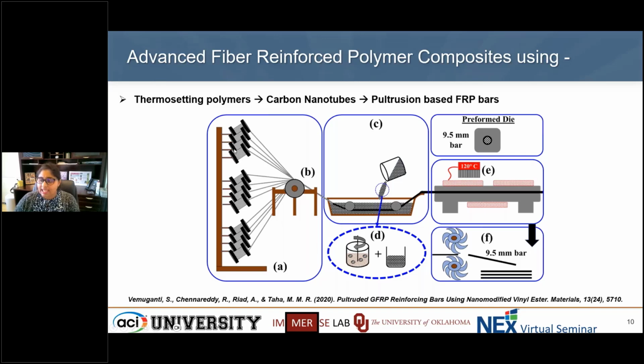We set up a lab-scale pultrusion method where we have an epoxy vinyl ester resin bath, which has fillers in it, which are carbon nanotubes. The way to achieve good homogeneous dispersion of these fillers is through two methods called sonication and mechanical stirring. That helps a more homogeneous dispersion by breaking those weak van der Waals forces and lessening the number of agglomerates, because with filler materials that dense, you tend to have more agglomerates. With a preformed die, we're looking at a number 3 bar. We have a heated die here and the bars coming out.